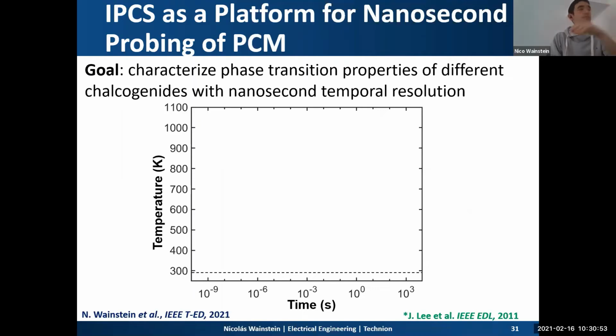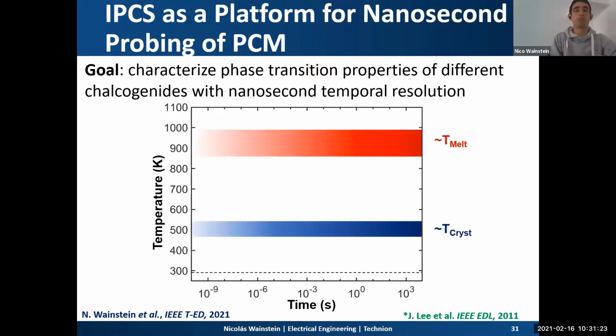And as previously discussed, the phase transition in chalcogenides is thermally activated, and the kinetics can span orders of magnitude in time, from several minutes down to sub-nanosecond timescales. And the temperatures required for the transitions can go up almost to or beyond 1000 Kelvin. Generally, the chalcogenides have a crystallization temperature around 200 Celsius or 500 Kelvin, and the melting temperature is around 700 Celsius or 1000 Kelvin. And the self-heating in PCM devices requires temperatures that go up to the melting temperature, which is something around 1000 Kelvin, and timescales of nanoseconds.